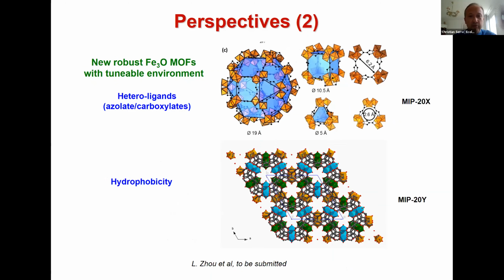There are other ways also to tune the redox potential and the Lewis acidity of the oxocluster, which is to change the ligand. Of course, you could change the functional group on the ligand to have a donating or accepting group. But a recent result that we obtained is to have, instead of a pure polycarboxylate ligand, an azolate carboxylate ligand, so pyrazole carboxylate here, and with iron we form this polymorph of MIL-101. Another example is this recent more hydrophobic macroporous iron MOF. As we know that water plays an important role in the DeNOx reaction, it will also change the affinity with water and therefore tune the catalytic activity.